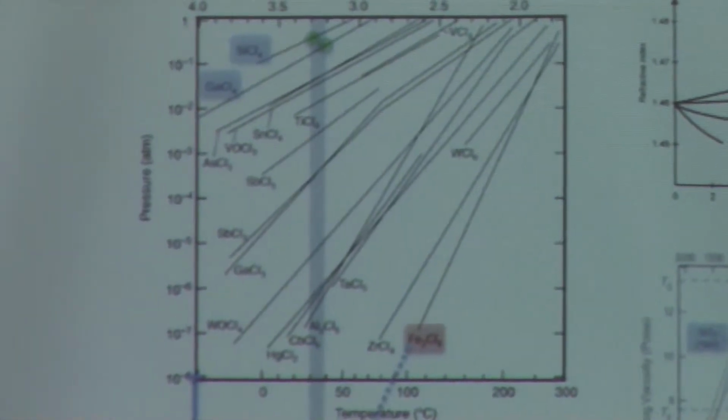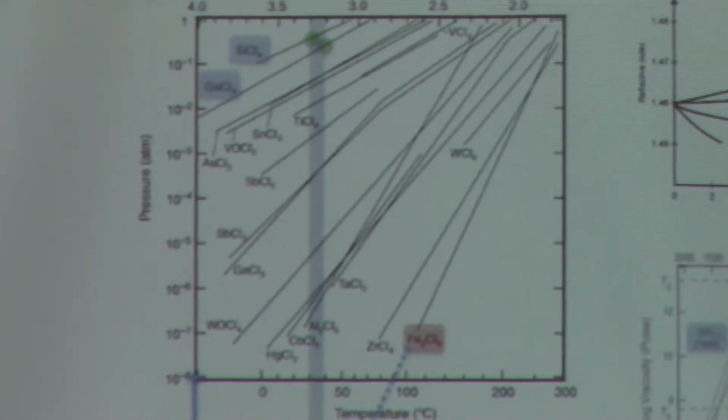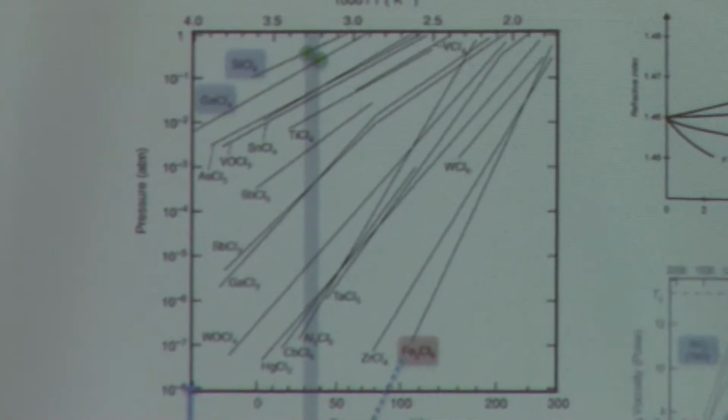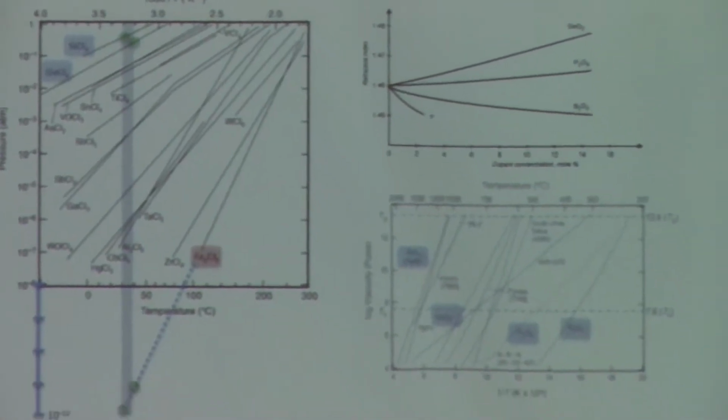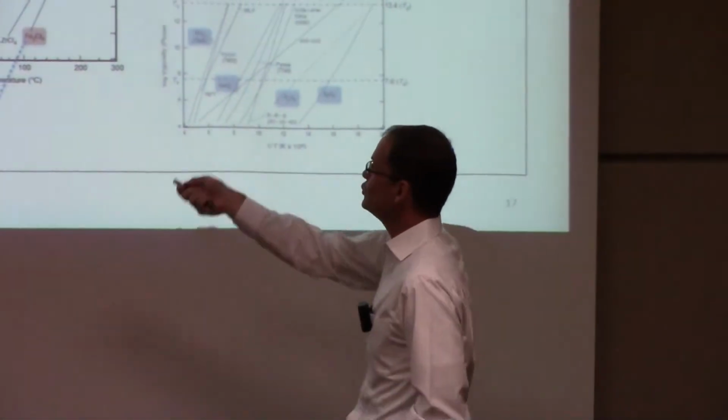Now this is beautiful because at any given temperature, there's a huge 12 orders of magnitude difference between the stuff you don't want and the stuff you do want. Fantastic. It's self-cleaning. So you can have a pretty crappy pool of liquid. You warm it up, the vapor begins to evolve off. It's 10 to the 12 times purer than what was in that liquid. Great, so that's good.